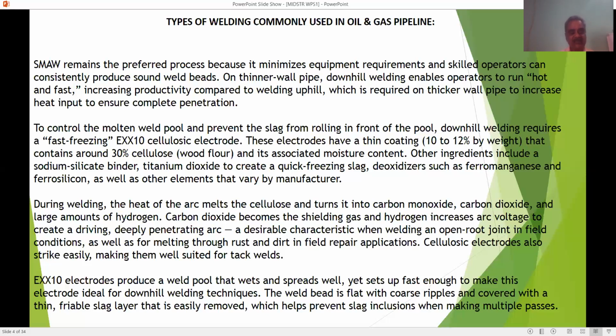E6010 electrodes produce a weld pool that wets and spreads well. It sets up fast enough to make this electrode ideal for the downhill welding technique. The weld bead is flat with coarse ripples and covered with a thin friable slag layer that is easily removed, which helps to prevent slag inclusions when making multiple passes.